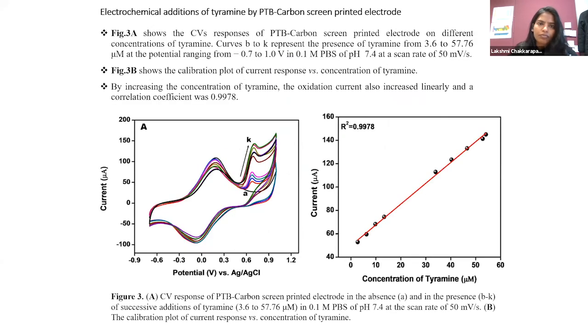And then we use this polymer electrode in order to analyze tyramine at different concentrations. For example, we do a step-by-step addition of tyramine, and then we analyze the current response. So from this figure 3, the tyramine concentration is 3.6 to 57.76 micromolar in phosphate buffer solution, pH 7.4 and the scan rate 50 millivolt per second.